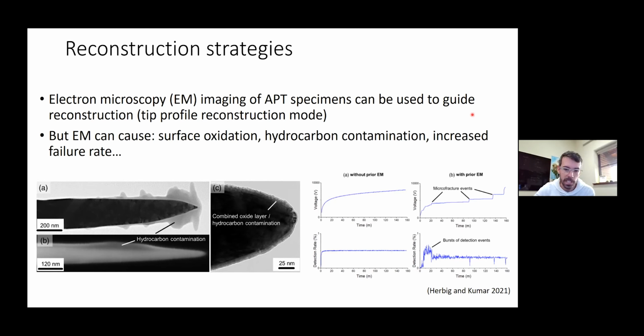And this is really nicely illustrated in this study by Herbig and Kumar, that could image the contamination layer and the effect it has on the data quality, including noisy data and also microfractures. So we basically want to avoid this strategy of having some intense electron imaging of all of our tips in order to increase our chance to get good data.